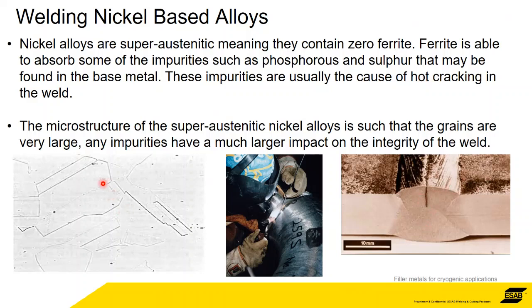Because of the grain size of the nickel alloys, as I mentioned, the grain size is very big, and the number of grain boundaries is very small. So in terms of strength and toughness in liquid solution, these don't want to hold together, and they're very prone to impurities. Impurities would generally come from your base metal. So any traces of phosphorus and sulfur affect the microstructure even worse, and it changes the solidification temperature. So you have areas that basically don't solidify quick enough to hold the weld together. Does that explain it? Parocchi, you got anything else? Good enough, sir. Okay. Good.